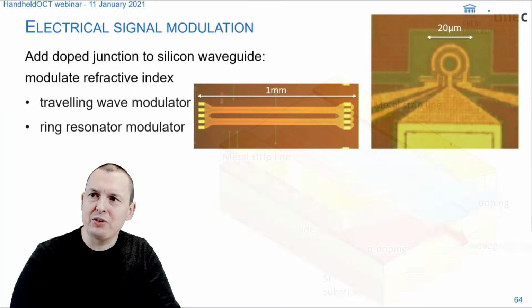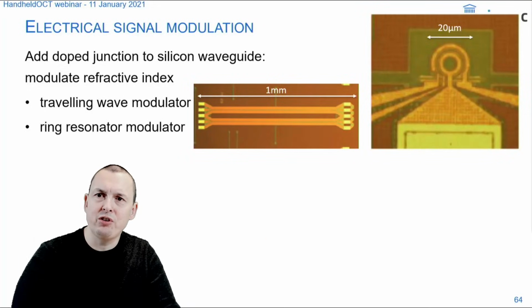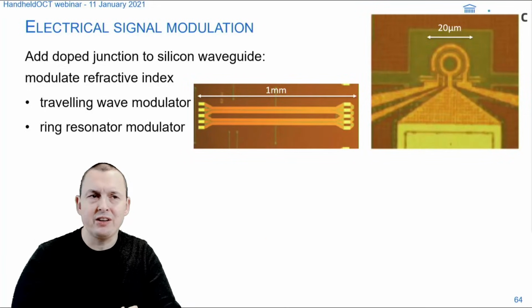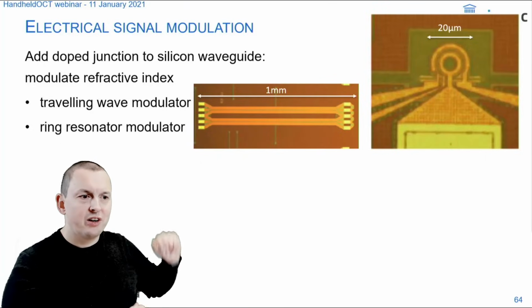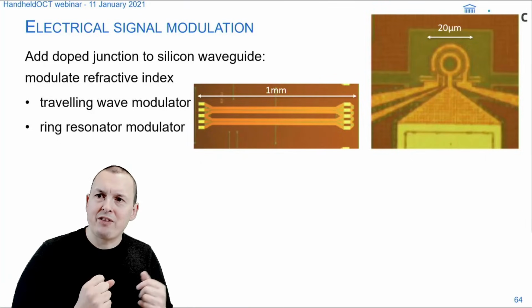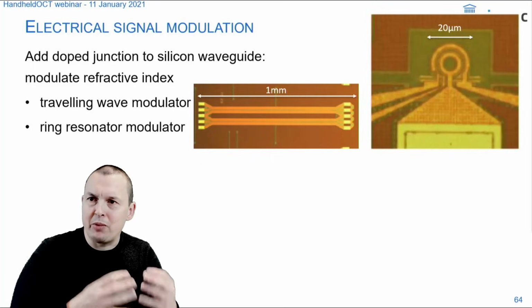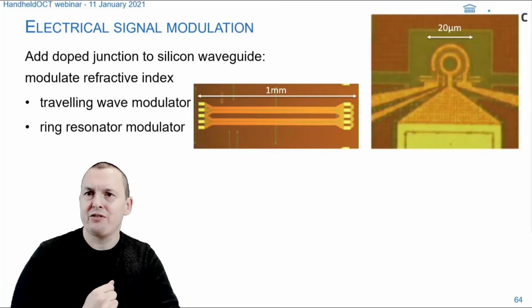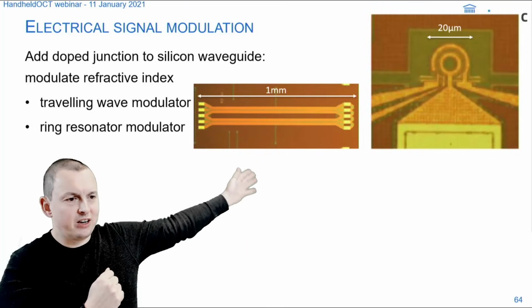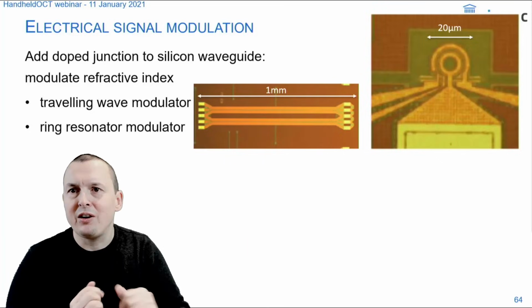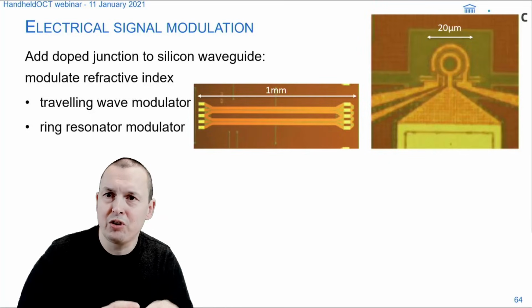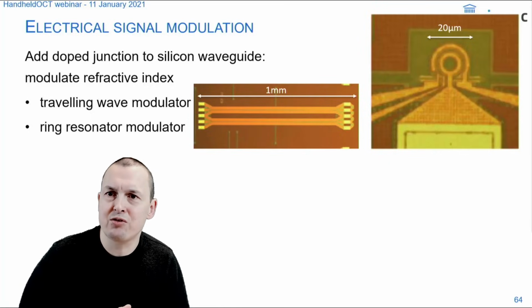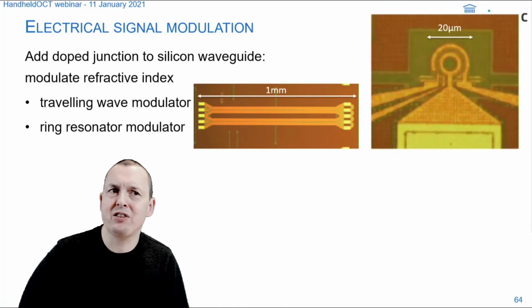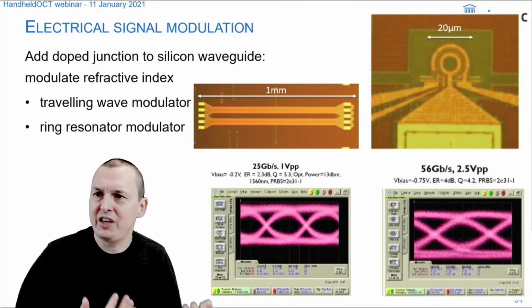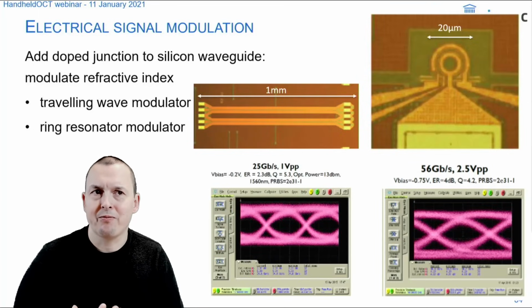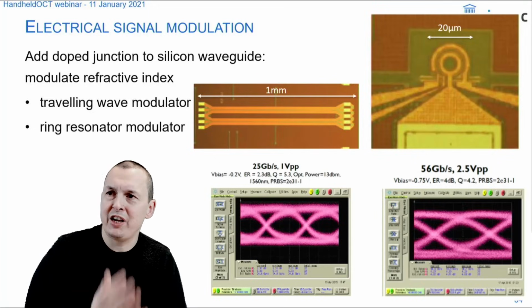So that allows you to do electrical signal modulation, and you can do that in different geometries. You can do that in the left one by using a traveling wave electrode and a Mach Zehnder interferometer. So you embed this modulator inside an interferometer, or you modulate it in a ring resonator, which we see on the right, where you put your diode inside a resonant structure, and then you change the resonant frequency of the wavelength. And we see that that works pretty nicely.